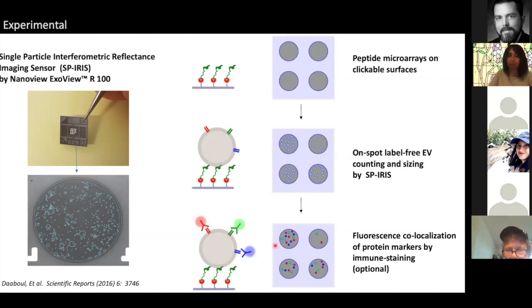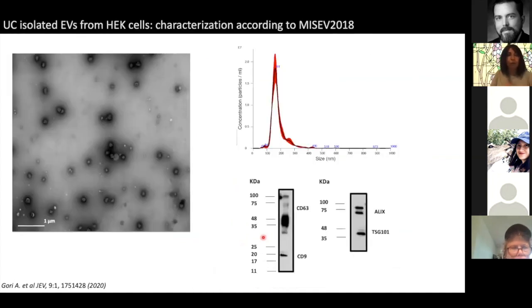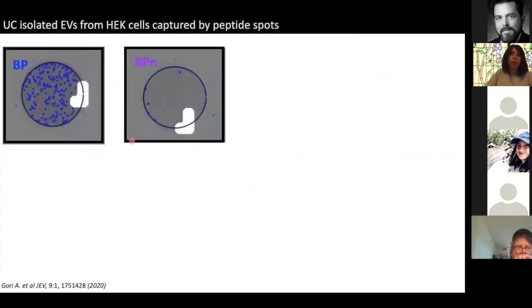And then optionally, we can add fluorescent antibodies for a fluorescence colocalization of protein markers by immunostaining on the surface. And so we started from a sample of EVs isolated by ultracentrifugation from a HEK cell line culture that, according to the MISEV 2018 recommendations, were extensively characterized by transmission electron microscopy, by nanoparticle tracking analysis, and by Western blotting to confirm the presence of external and luminal typical EV markers. And then this sample was incubated on the peptide array.